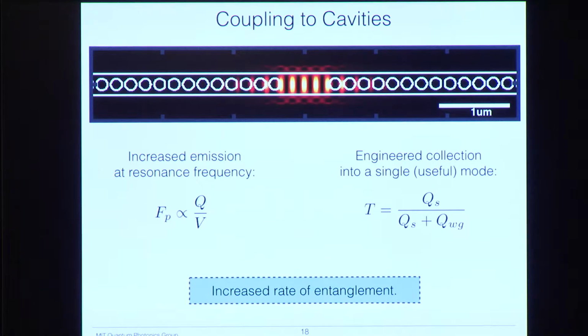But now we have to make this, and as you noticed, it's inversely proportional to the volume of the cavity. And so we want a very small cavity. And so of course, we want a nanophotonic cavity, and then we need to create a nanophotonic cavity. So how we do it, instead of using big Fabry-Perot mirrors, we create a photonic band gap. This is created with a periodic modulation of the index of refraction, and this stops light propagation at a specific frequency. And then we create a defect in the center, which allows light to stay only at the center and not propagate into this mirror created by this photonic band gap.